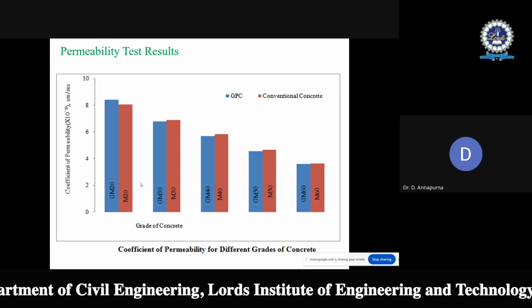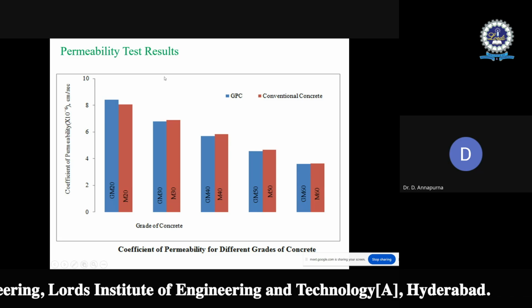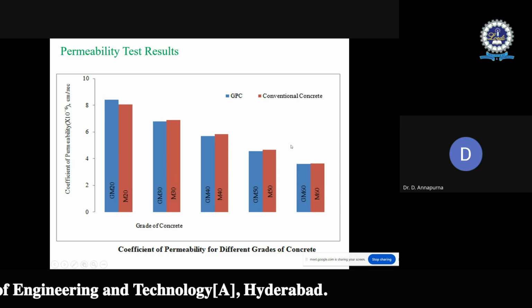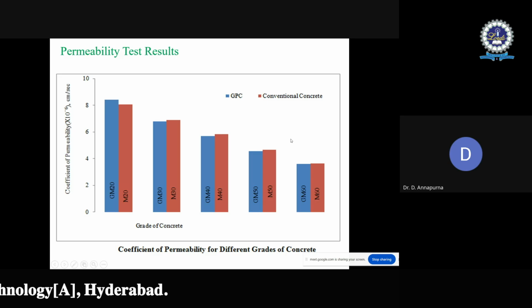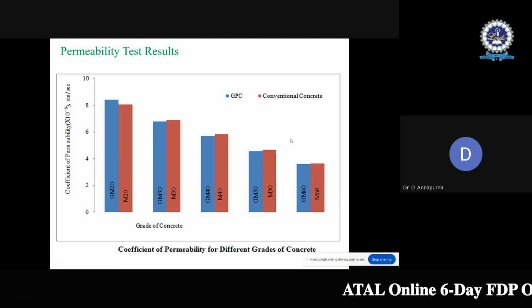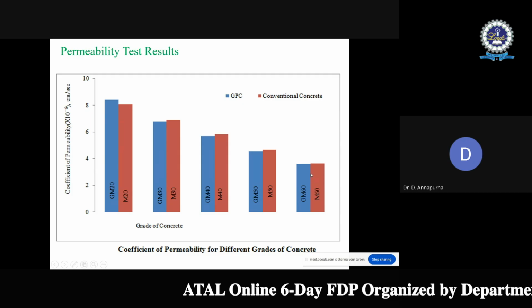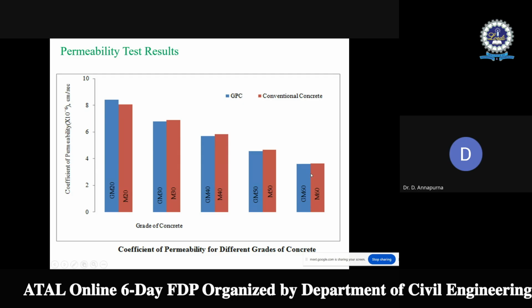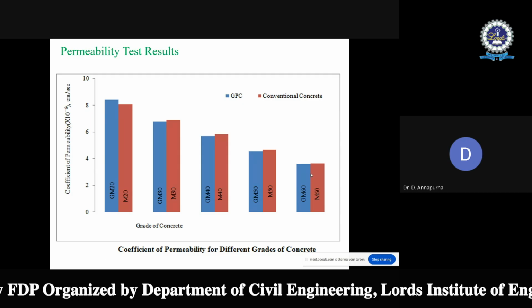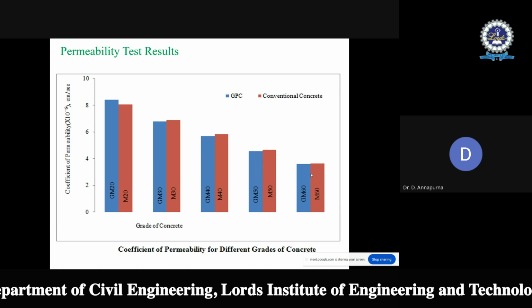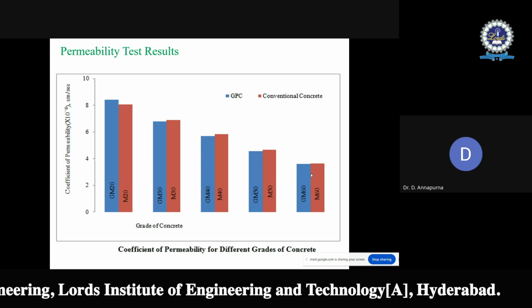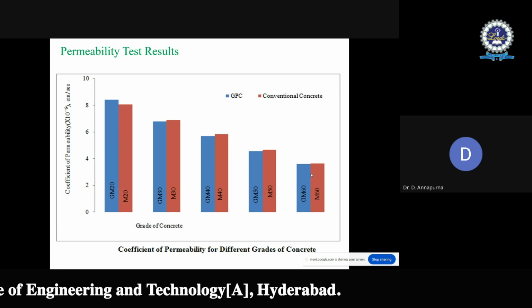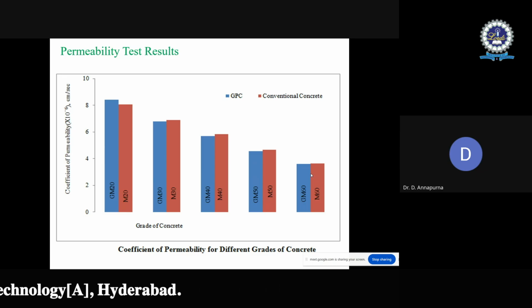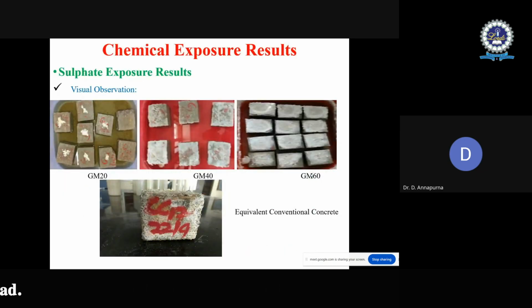Then the coefficient of permeability. The permeability test is conducted on the geopolymer concrete and the conventional concrete of the same grades. It is seen that as the grade increases, the coefficient of permeability of both is almost the same. It is depicting the same as that of the water absorption characteristics. So out of this, we can say that the penetration characteristics of geopolymer concrete and conventional concrete are almost the same. It is behaving in a similar way.